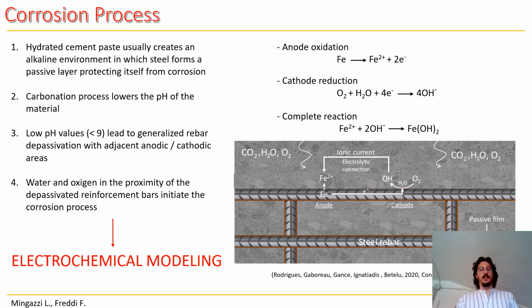Once the carbonation front reaches the reinforcement bars, the passive layer protecting the rebar from corrosion is lost, and therefore the corrosion process can start due to the presence in the adjacent areas of oxygen and water. The carbonation process leads to a generalized depassivation of the reinforcement bars, which translates into a generalized corrosion process. The corrosion process is characterized by two semi-reactions, one for the steel anode oxidation and the other for the oxygen cathode reduction, which when summed together provide the complete corrosion reaction.